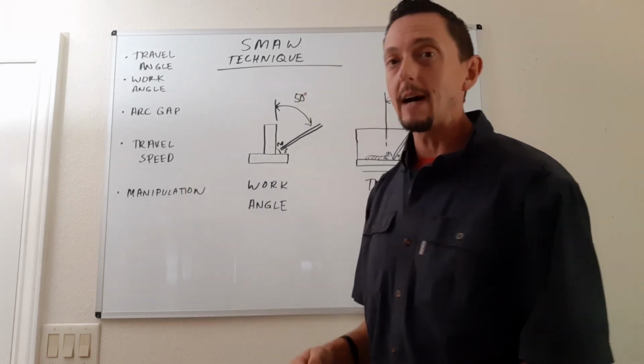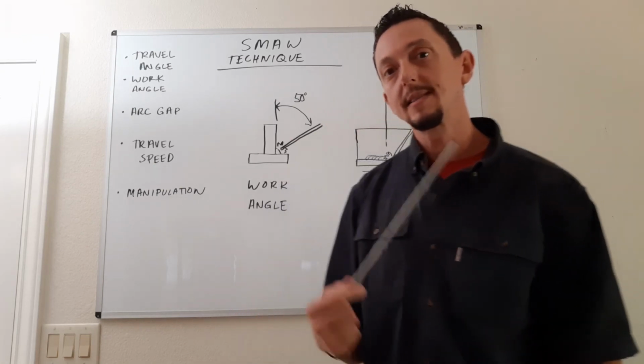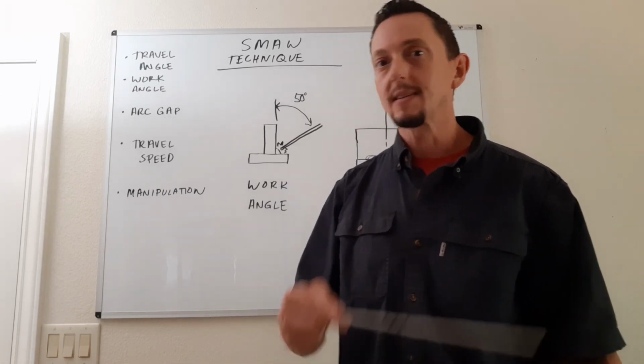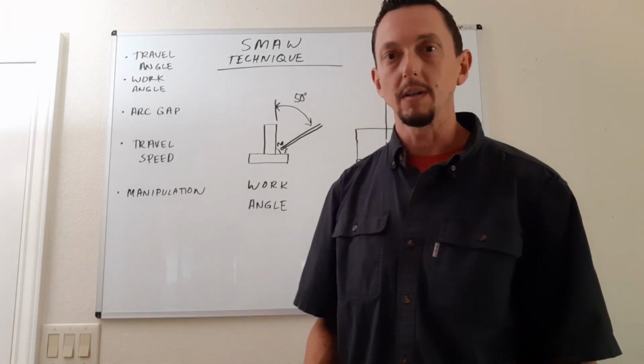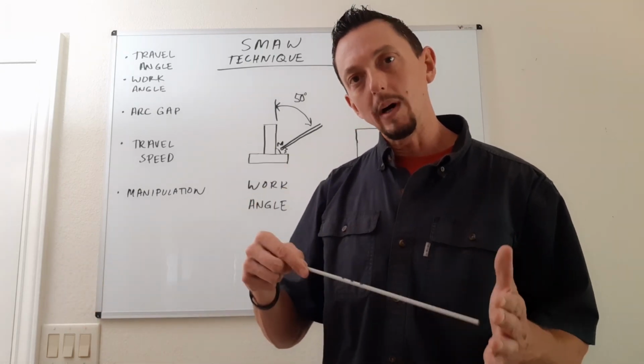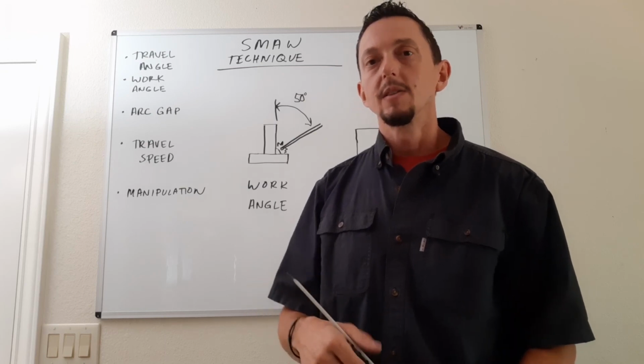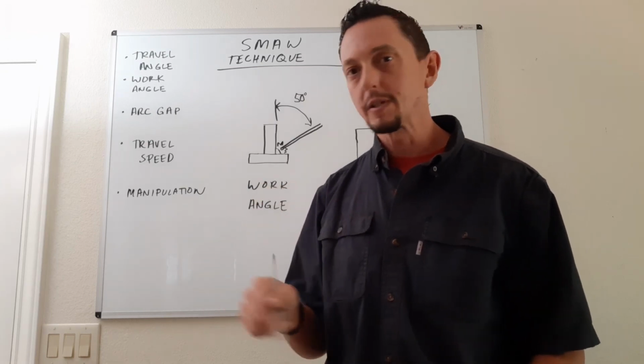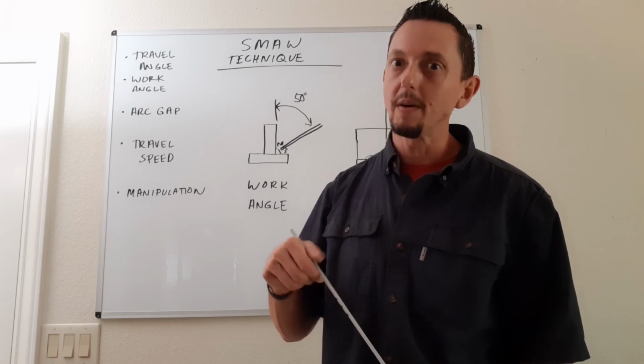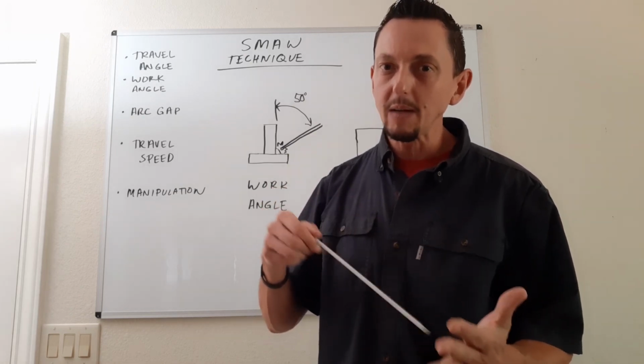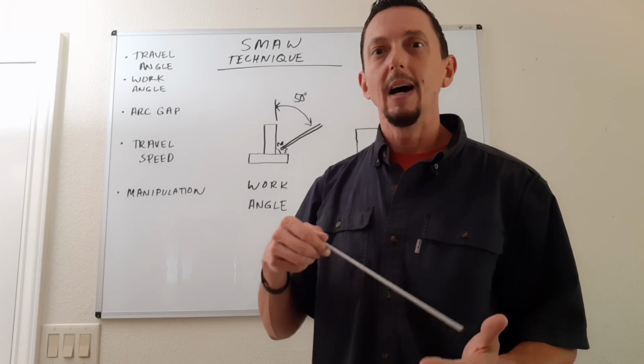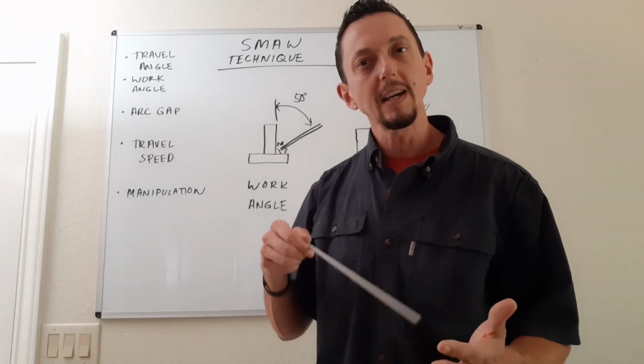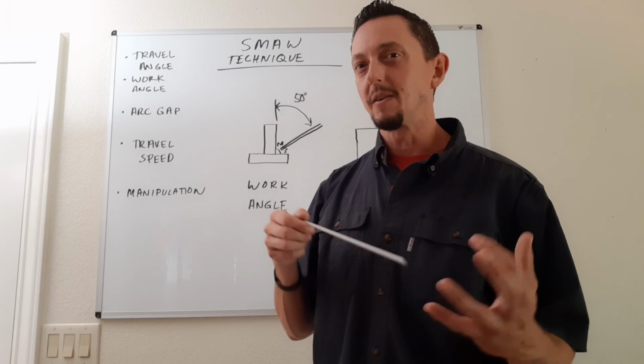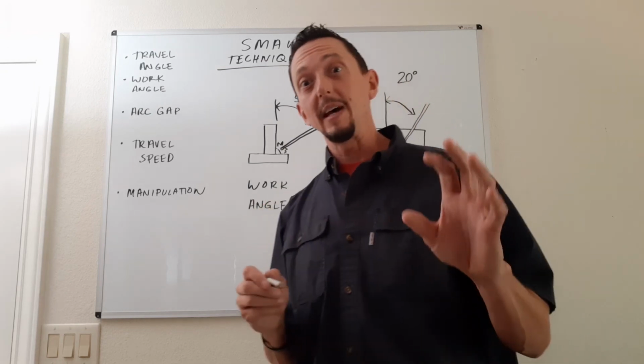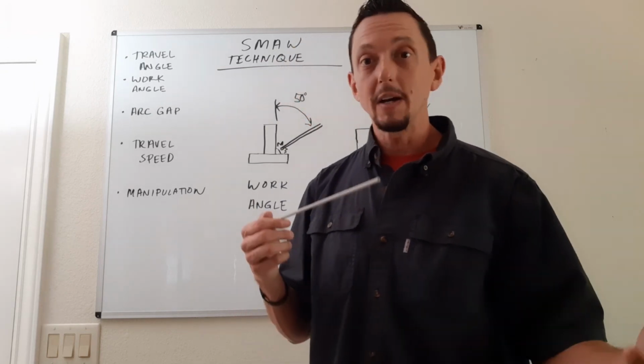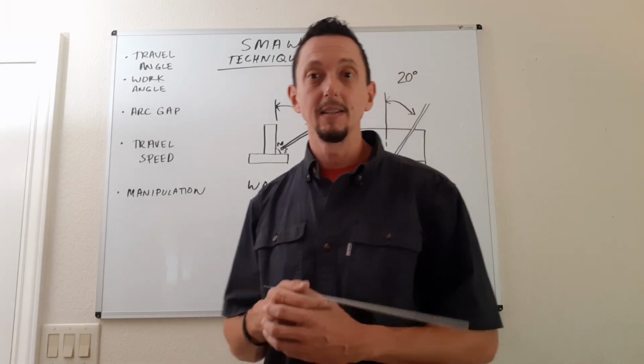Now, travel speed. Travel speed's pretty self-explanatory, although I see most new welders in any process, they just are going way too fast typically. They aren't really giving the weld pool a chance to fill up. So just keep that in mind if you're running your first bead ever, go slower than what you think. Especially with stick welding, once you get the arc started, which can be kind of difficult when you're first starting, maybe you're a little wary of it, or it's the first time that you're welding, so that arc flashes, and you got your PPE on, but it's still a little bit scary.